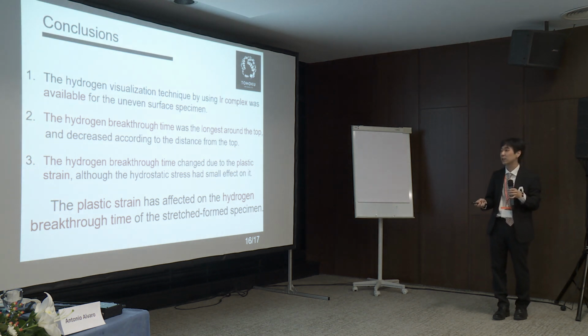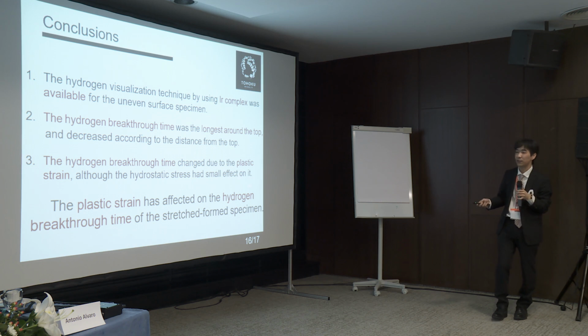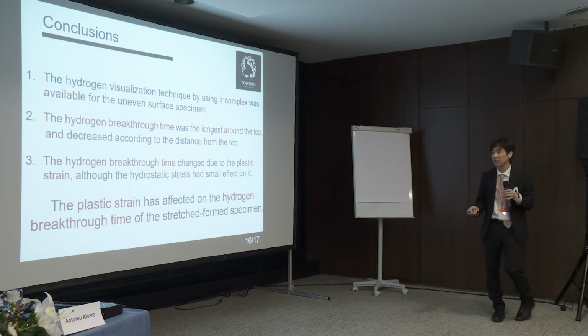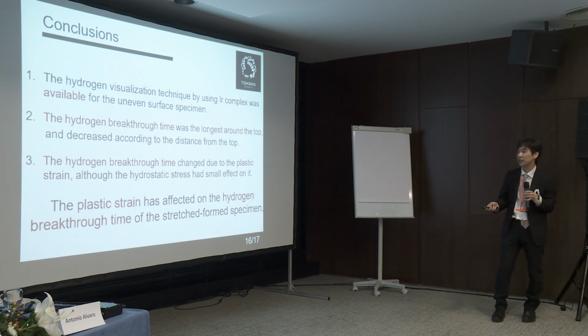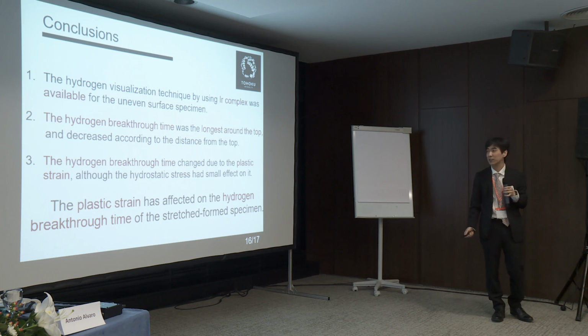Finally, the hydrogen breakthrough time changed due to the plastic strain, although the hydrostatic stress has a small effect on it. So we can conclude that plastic strain has affected the hydrogen breakthrough time of a stretch-formed specimen. That's all of my presentation.